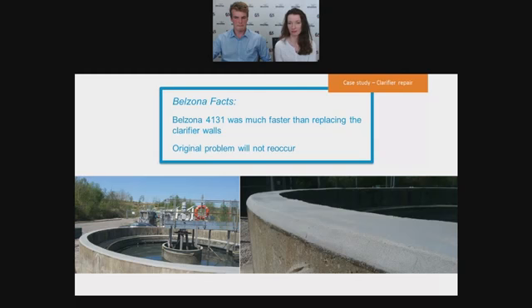This had 2 major benefits over a traditional concrete repair. Firstly, by using a Belzona material, a repair could be completed in a fraction of the time it would have taken to knock down the walls and rebuild them. As well as this, the material's chemical and impact resistance prevents the original problem from recurring. The reason why it prevents the problem from reoccurring is that the Belzona concrete epoxies are non-porous. Therefore, you eliminate water ingress, and therefore freeze-thaw cycles cannot damage the material.